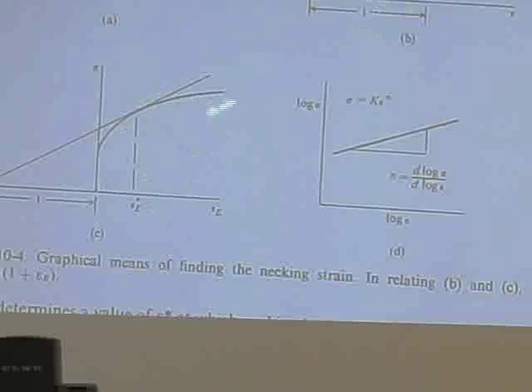Both of these are called the Considere construction because some French mathematician came up with it once. Or you can plot the log of stress versus log of strain, get the slope, which is equal to n, and you can prove that your necking strain for a circular tensile bar is just equal to your strain hardening exponent. Again, anybody have an idea what the strain hardening exponent for steel or aluminum, low carbon steel or aluminum might be? It's going to be something on the order of 0.2. Could be 0.15 for a higher strength steel, could be 0.25 for a lower strength steel.